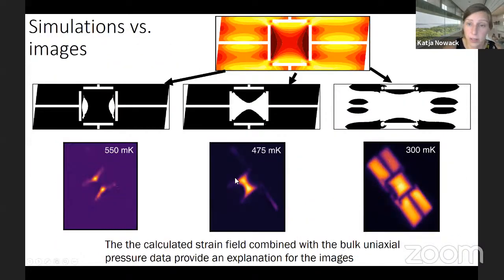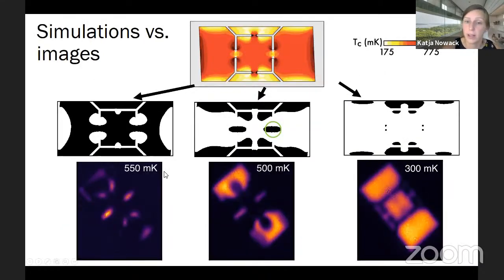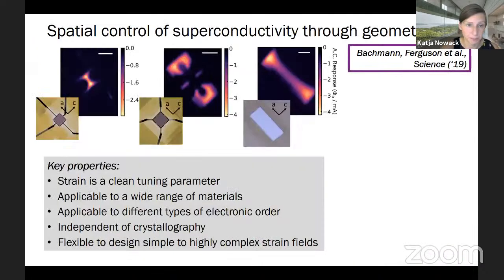If we compare that to our data, we can do that by pulling binary frames from this map. If we look, for instance, at 550 millikelvin, all the regions shaded in black here will not be superconducting yet, but all the regions shaded in white will already be superconducting. We can do that for different temperatures, and we find remarkable agreement between these simulated maps and the images that we've taken. We can do that for the second device as well and find similarly good agreement. And so this is exciting because we solved this puzzle of what is the source of this unusual transport behavior.